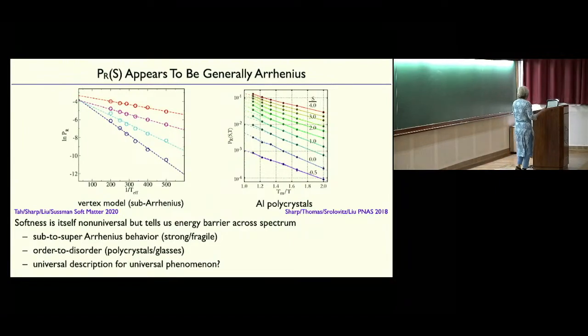So this softness itself, right? Softness is non-universal. The definition of softness is the same for all of these different temperatures, right? But it's different for aluminum than for the vertex model, right? And yet the emergent behavior of softness, the fact that it captures the energy barriers, is universal. And it's universal across the whole spectrum from order to disorder, from sub-Arrhenius to super-Arrhenius behavior. And because of that, I would argue that it's a reasonable universal description for a universal phenomenon. It's a reasonable starting point.